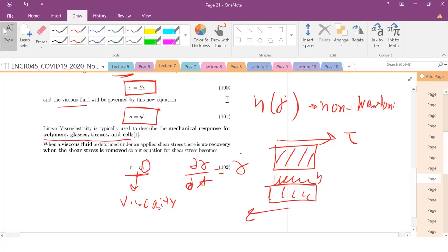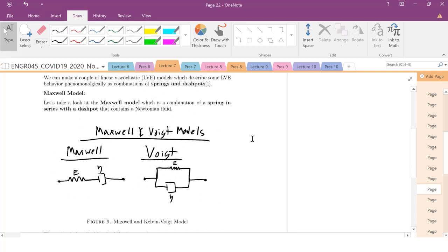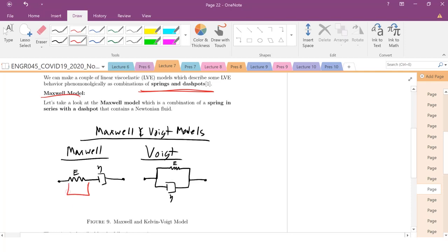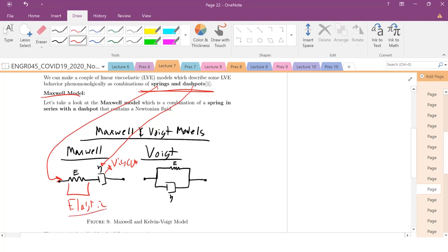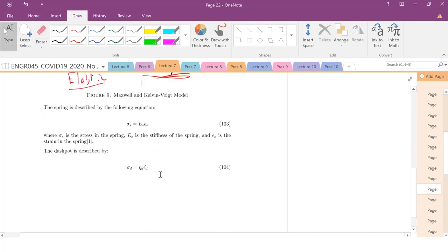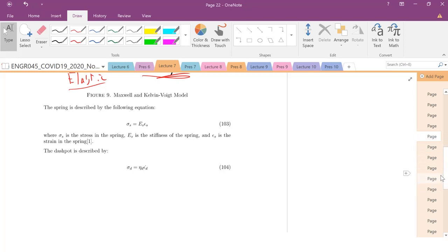There are lots of ways to describe the viscoelastic behavior of polymers. One of the first is to look at the viscous and spring components by approximating your material as a series or parallel connection of springs and dashpots — giving you the Maxwell and Voigt models. The spring is your elastic term and the dashpot is your viscous term. You can essentially describe the equations governing the mechanical response this way.